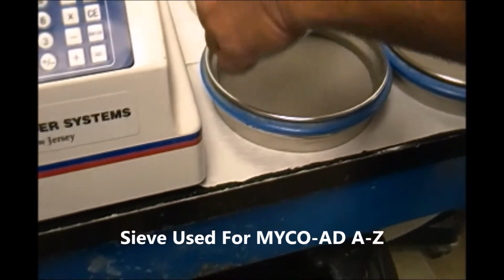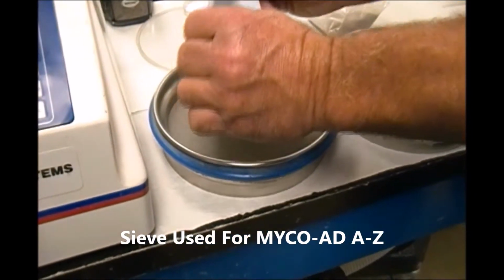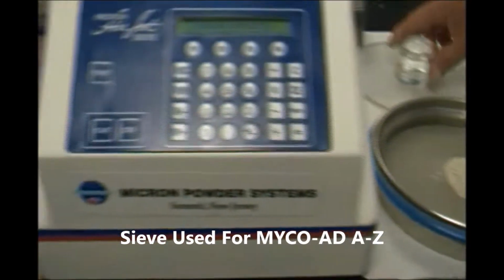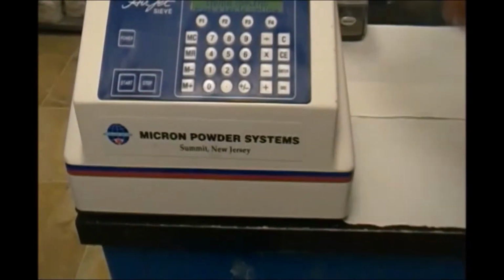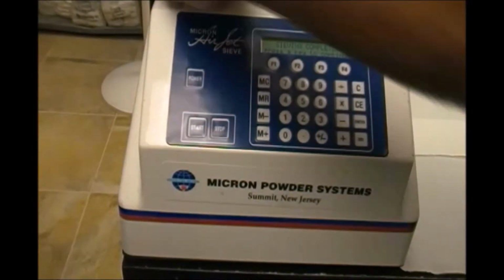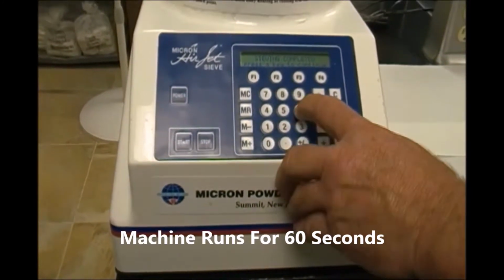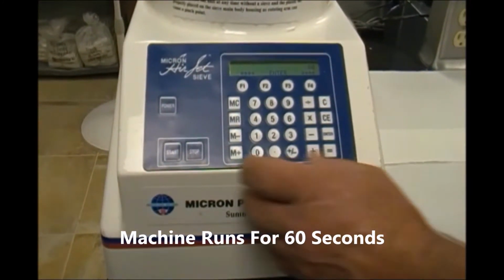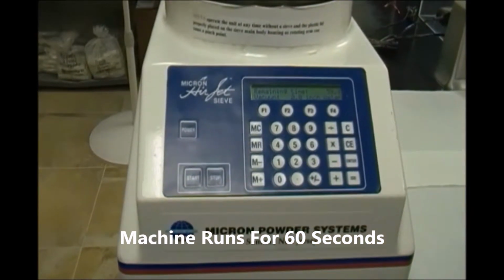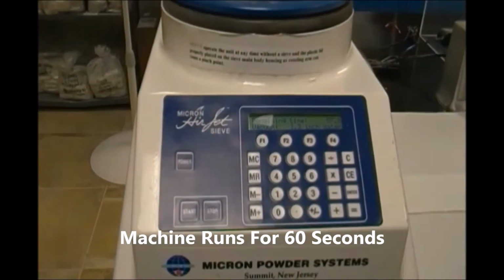Next, we will place the product into the sieve for the test. The sieve will be placed in the Micron powder machine for analysis. The machine is set to run for 60 seconds. After the 60 seconds, we'll measure the residual product, which will allow us to determine what percentage of the product is of ideal particle size.